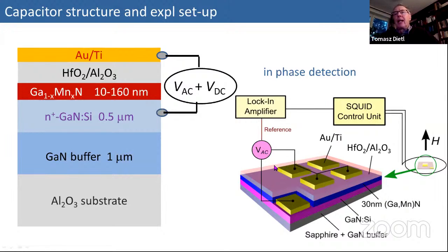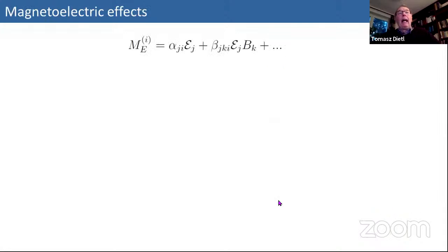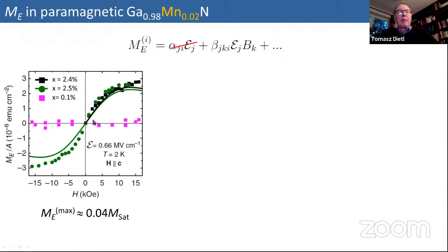And for technical reasons, it is good to make many capacitors because, as you perfectly know, breakdown of a capacitor somehow increases the chance with surface. So if you make many small capacitors, you can eliminate bad capacitors and work on good capacitors. That's a technical issue. We measure dozens of these capacitors at the same time, eliminating those which don't work, which show that capacitance is not as we expect. As we said, if we have a paramagnetic material, time reversal symmetry is obeyed and not broken. So we should have dependence on the magnetic field, and indeed we see that there is no effect: the magnetization induced by electric field is zero in zero magnetic field, but it starts to grow with the field exactly as predicted.